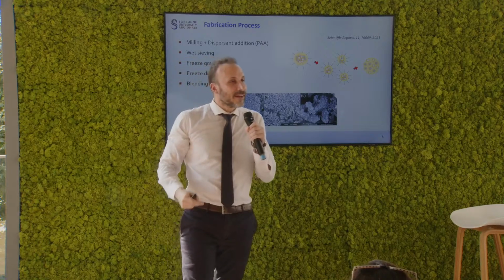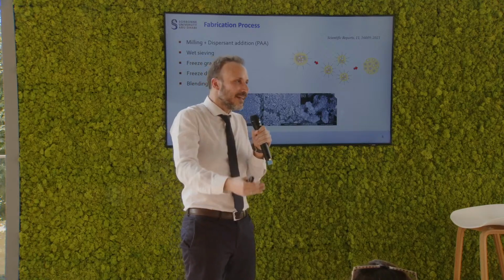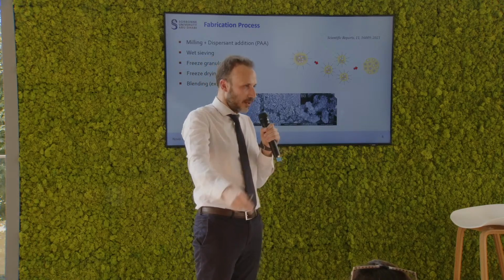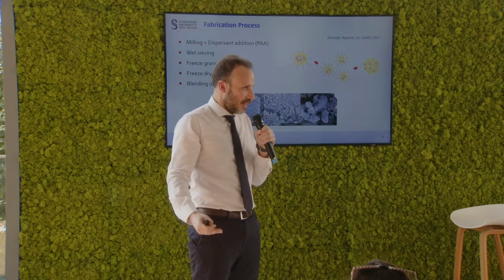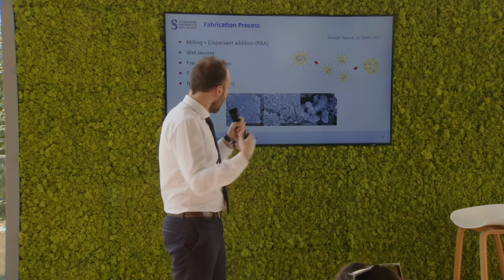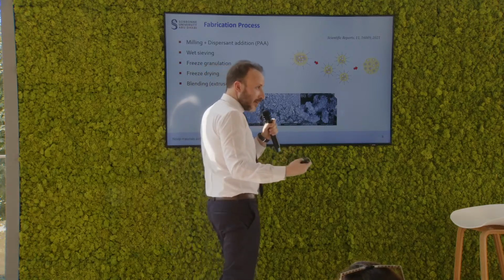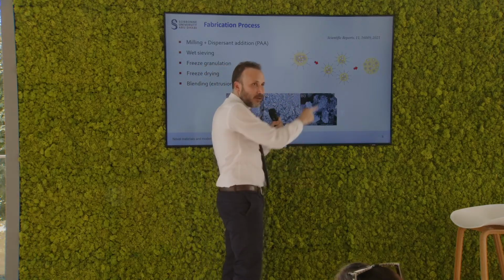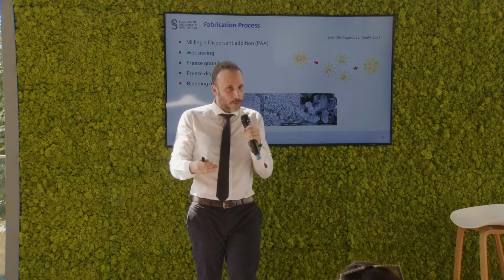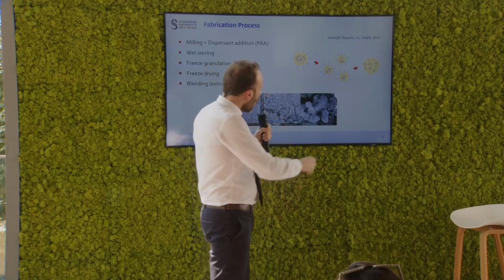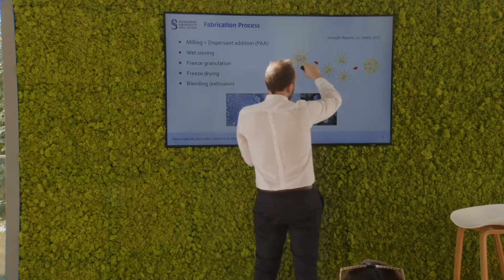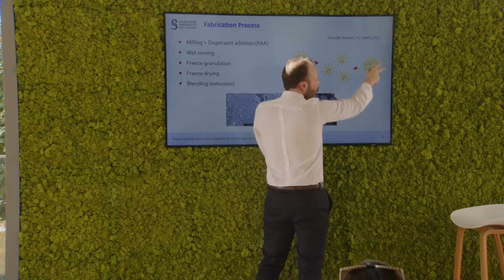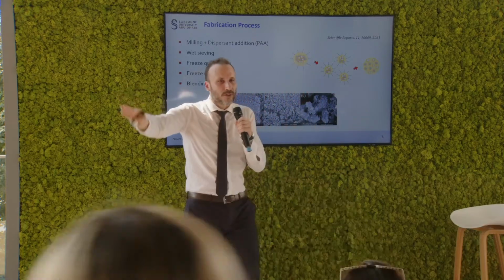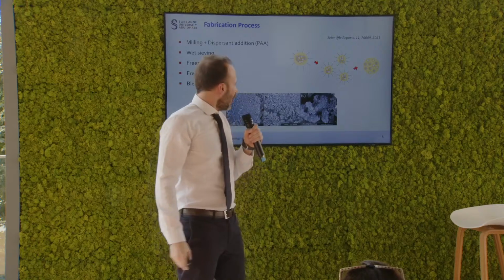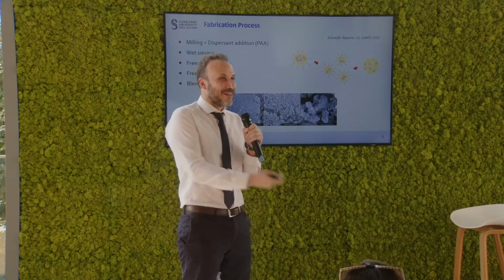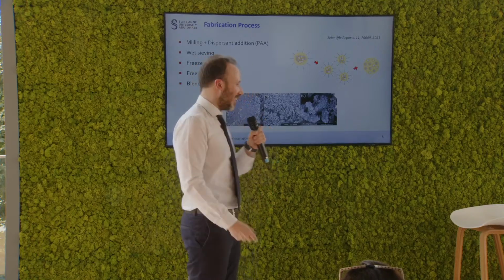So first we start by increasing the temperature in order to increase the mobility of the polymeric chains, so it can be mixed easier. And then we advance the pressure, we increase it in order to break that granule down to much, much smaller bits until eventually all the nanoparticles that were contained in the granule are freed to move and disperse throughout the entire body of the matrix. And this is how we obtain what we believe is a homogeneous material at the end of the day.